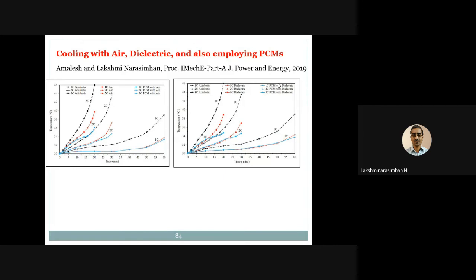Whereas if you go for 3C operation, the temperature exceeds the safe limit of 40 degrees. You go to 46 degrees. But now by adopting these methods, PCM with air or hybrid methods we can call, we are able to touch down below 36 degrees centigrade. This is what we have found out.